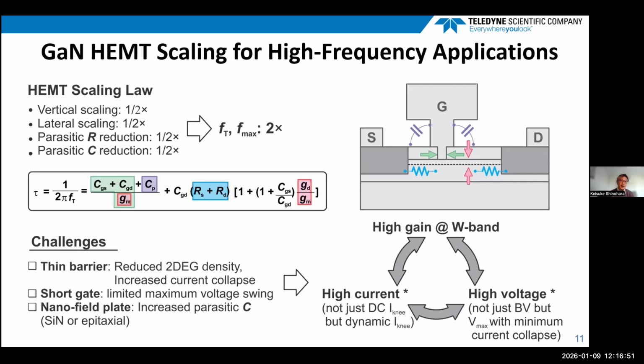However, there are challenges. In order to reduce the vertical dimensions of a transistor, we have to reduce the barrier thickness, which may result in reduced 2DEG density and increased current collapse due to increased capacitive coupling between the surface states and the 2DEG. And using a short gate for lateral scaling often limits the maximum voltage swing.